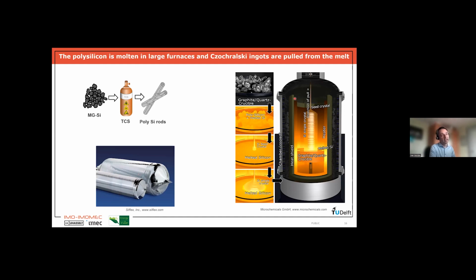So how does it work? Again, we have a reactor. In this case, we have to heat it up even higher to temperatures above 1400 degrees, which is the melting point of silicon. And we put a crucible, typically from graphite or quartz, into this reactor. And the crucible is filled with these polysilicon rods that we have grown in the step before. So we heat up these crucibles to more than 1400 degrees so that the silicon is in the molten state.